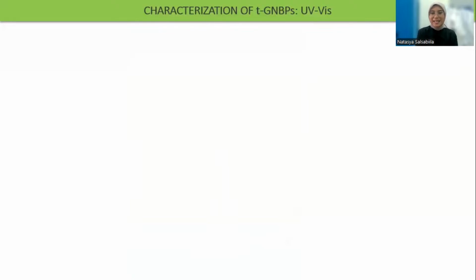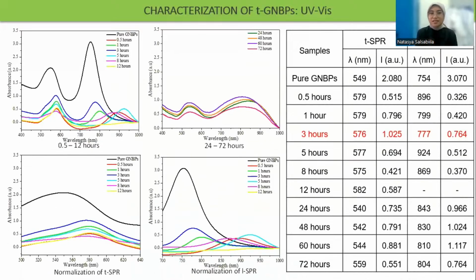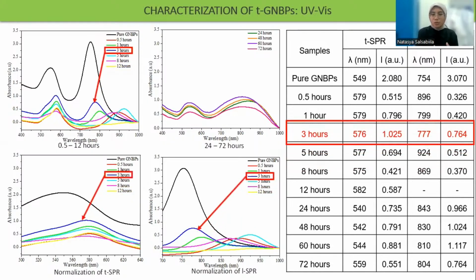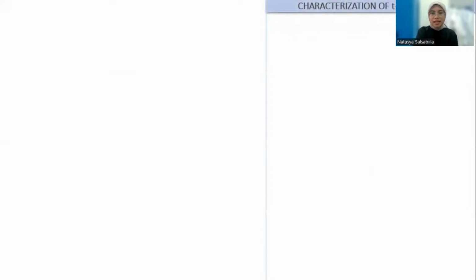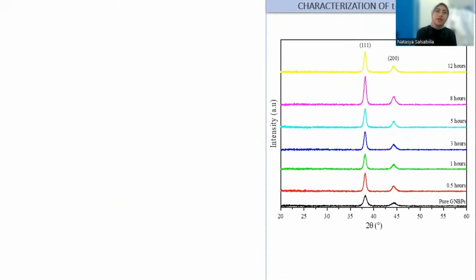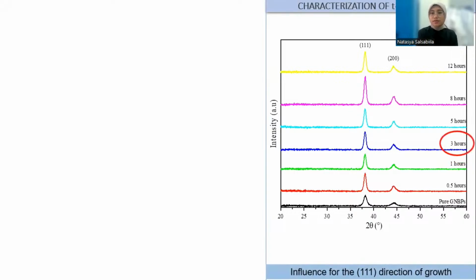Next, we move on to the TGNBPs, and this is the UV-Vis results of TGNBPs or thiol functionalized GNBPs. If you see here, in general, the spectrum shifted into the blue region, indicating a decrease in the aspect ratio, so a bit different from AGNBPs before, and the highest absorbance value is also obtained at 3 hours. With over 12 hours, the spectrum turned broader, indicating that the shape of nanoparticle is not bipyramid. Okay, this is the XRD pattern of TGNBPs, and based on this result, there is no additional peak as in AGNBPs before,